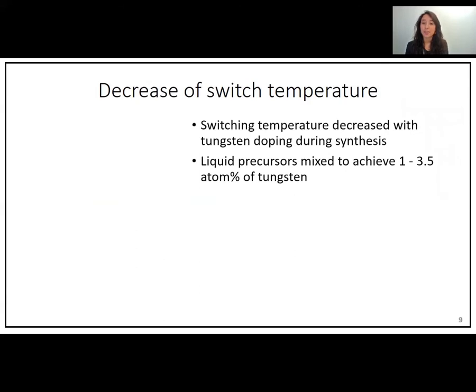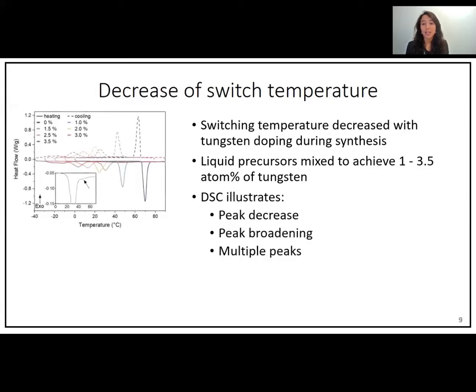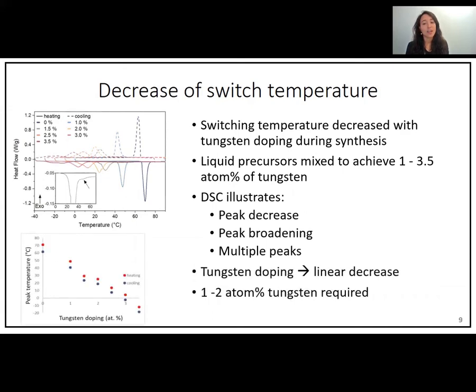The switching temperature challenge has been addressed through the addition of tungsten to the crystal structure. This is done during a synthesis by mixing the vanadium liquid precursor with the tungsten liquid precursor in different quantities to achieve from 1 to 3.5 atom tungsten percent. With the addition of the tungsten in the DSC, it is possible to see the decrease in the peak temperature. The peaks are broadening and also multiple peaks appear, which indicates different phases being present. The addition of tungsten decreases the temperature linearly, and therefore it can be tailored very accurately.